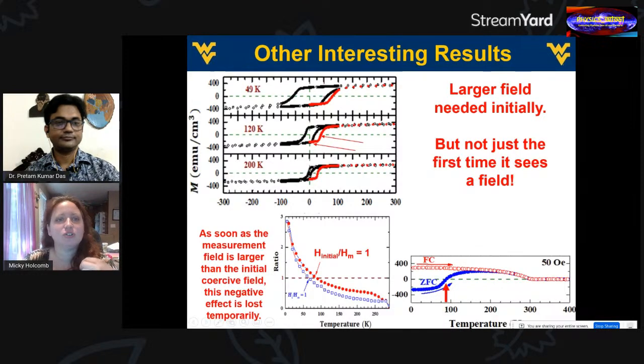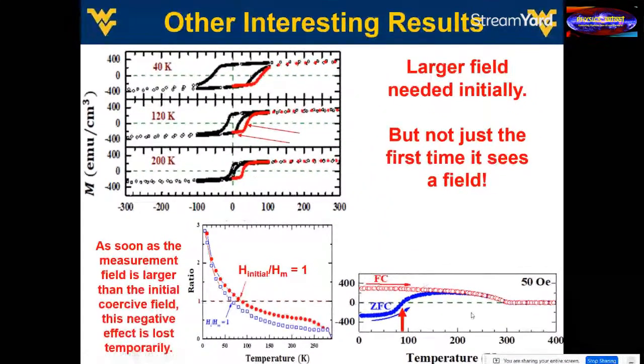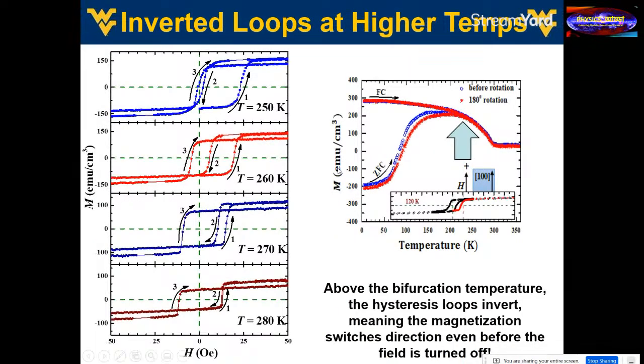So here we have loops at relatively small temperatures, 40, 120, and 200 K. All right. But what happens, so we're up to here on this curve. So 40, 120, 200 K. You'll notice in those ranges, you're having a lot of difference between the field cool and the zero field curves. But how about when we get a little bit higher, a little bit closer to where our ferromagnetism eventually goes away? Well, now some really weird stuff happens.